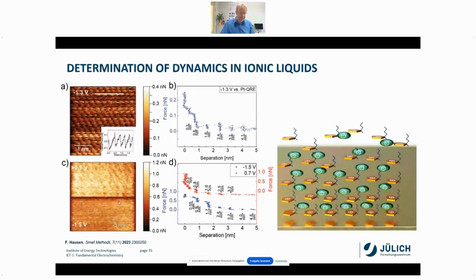we see something like this. So in this case, there's no crystalline structure to be seen, but we see if we change the potential, in this case from positive potential towards negative potential, that the friction changes. And if we look at the force distance curve, so penetration of the tip through these layers, we see that the layers also change. So the larger distances remain the dimension of the ion pair, whereas the interface distances change to cation and anion layer.